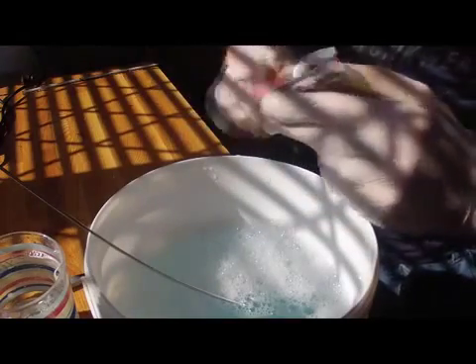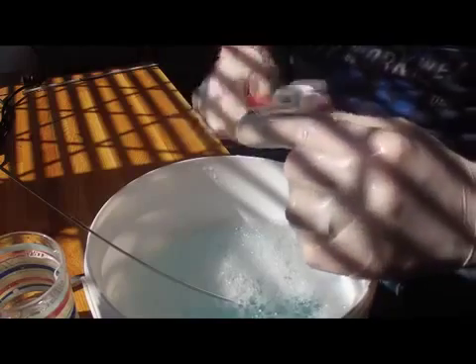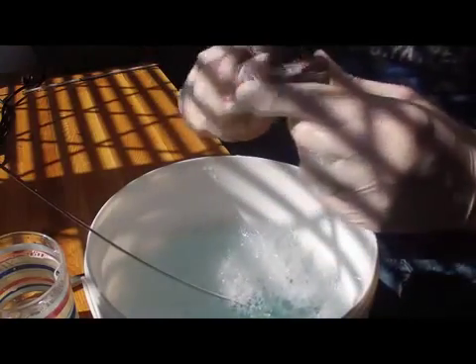Otherwise what you would do is take caustic soda. About five grams to a cup of water of caustic soda. And drop the pieces in there for a couple of minutes. That's all it takes. Two to four minutes, round about that. And what you'll get is this milky sort of look all over the metal. It basically attacks the metal. It's strong alkali. And it will dissolve the aluminium.